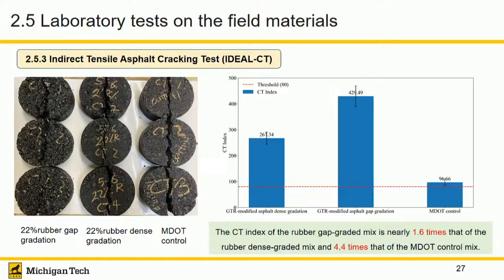Anyway, so we also tested our favorite test, called the DCT, here again. Of course, we also tested IDEAL-CT. That's another thing people are using. But really my point here is that the cracking resistance is pretty good, right? So this one is 4.4 times better than the regular materials.